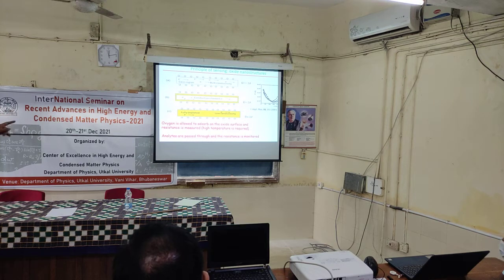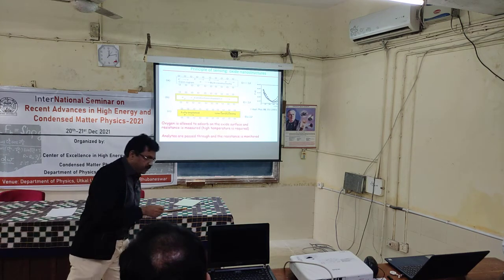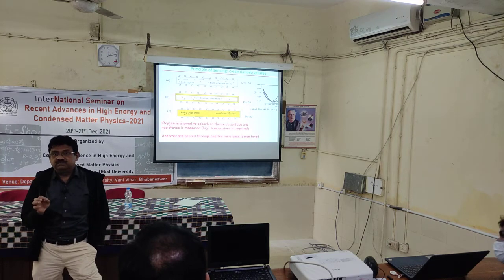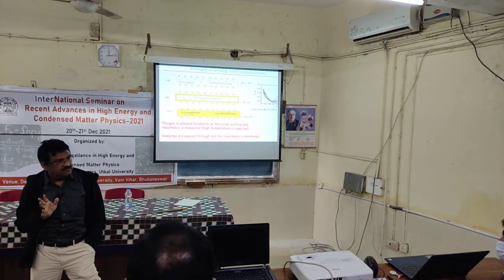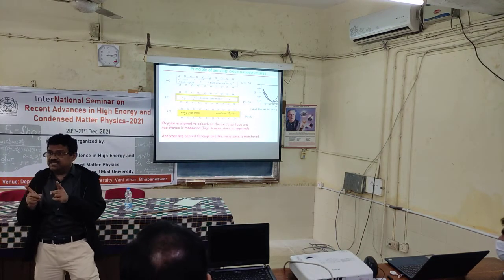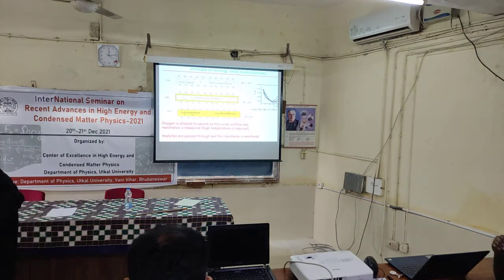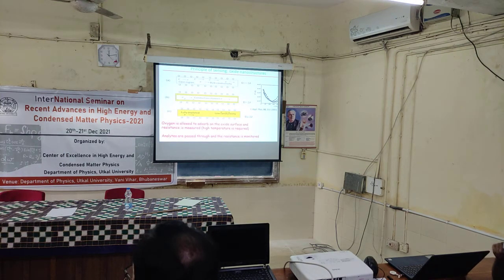That is what is happening beyond 150 degrees centigrade in oxygen. As I have mentioned before, the tin oxide based sensors operate around 250 to 300 degrees centigrade. That's why you need a high temperature. High temperature is not like 700, it is 250 to 300 degrees centigrade. Beyond that there will be a structural transformation, and you may not get back your initial state. So one should not go beyond 300. But between this range, it operates.